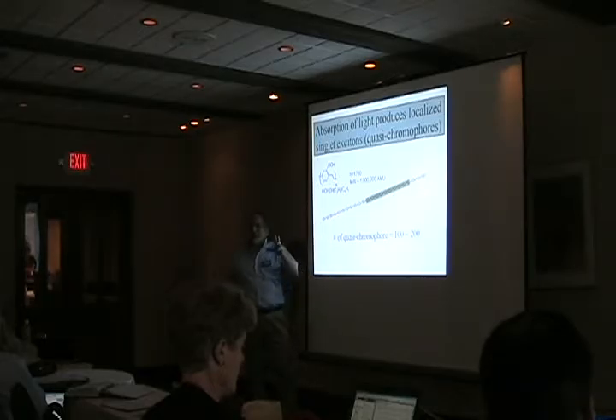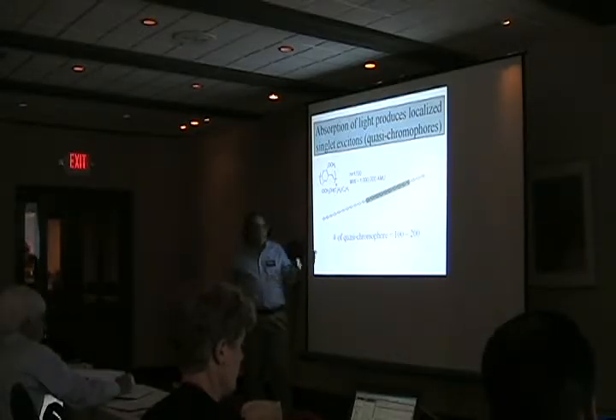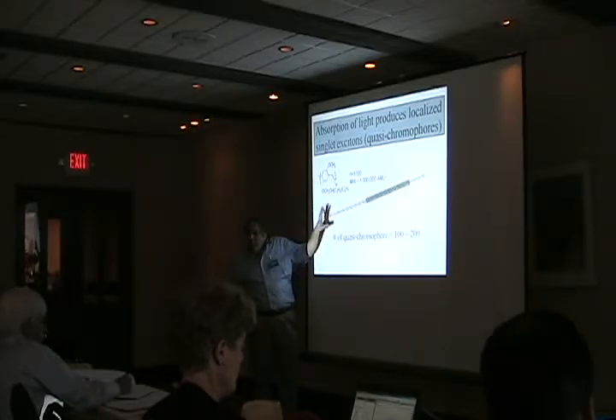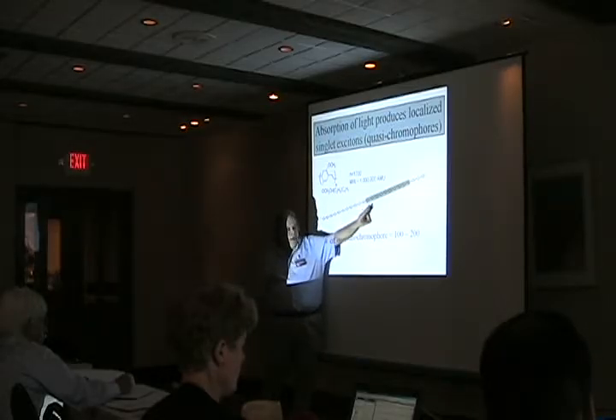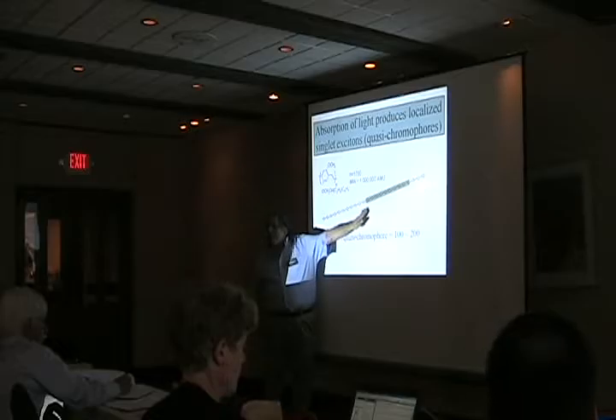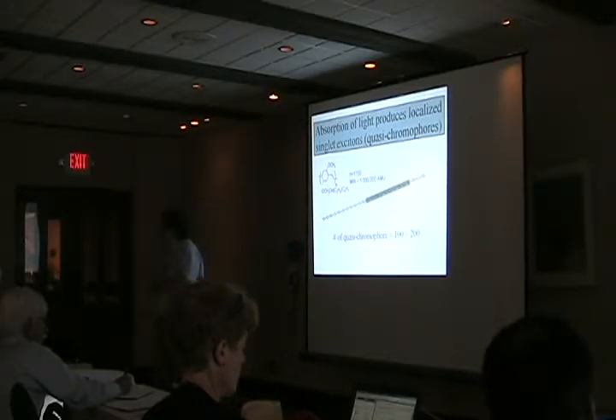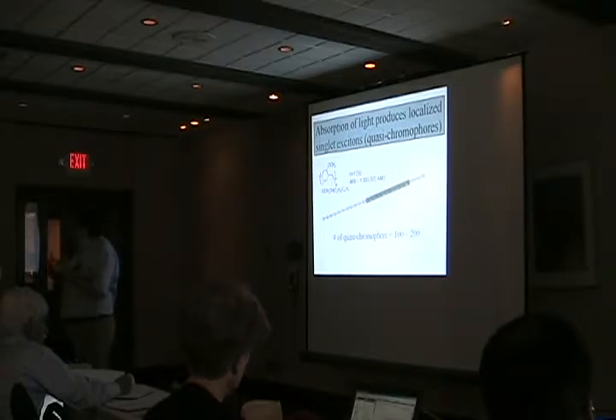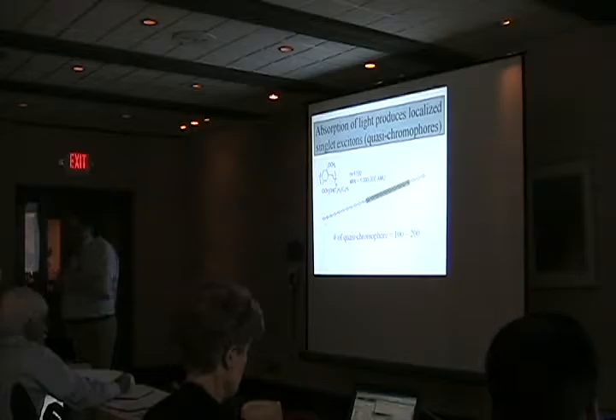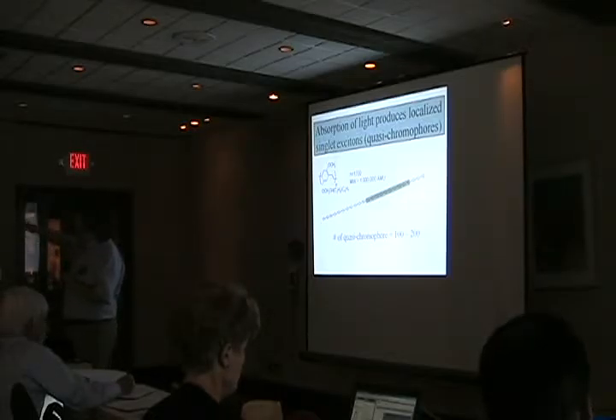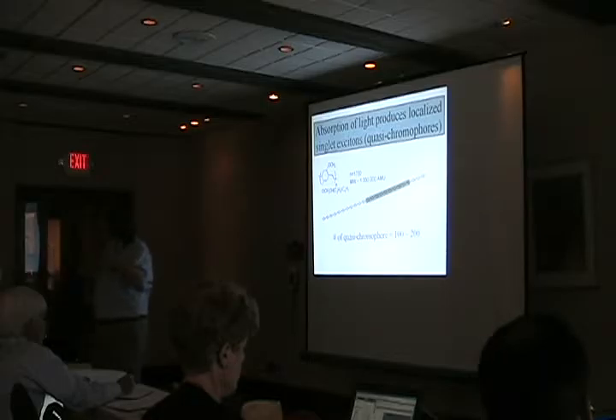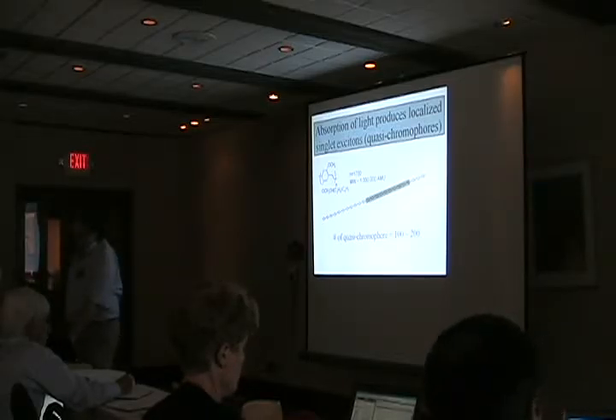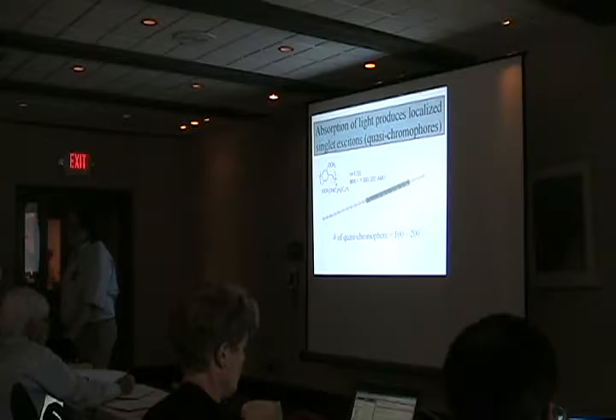It has some greasy groups on the side to help it become soluble and fold into a structure. And even in a system like this, if it were perfect and were symmetrical, due to electron correlation effects, optical excitations are limited in size in these systems to compact excitons on the order of 5 to 10 double bonds. Now, however, in a system that's perfect with no disorder at all, that would move at high velocity up and down the chain if you created it. In our systems, they're furthermore folded and so on, so those excitations become localized and primarily move, not by motion along the chain in a coherent way, but by Förster resonant energy transfer to hop to a nearby site of lower energy.